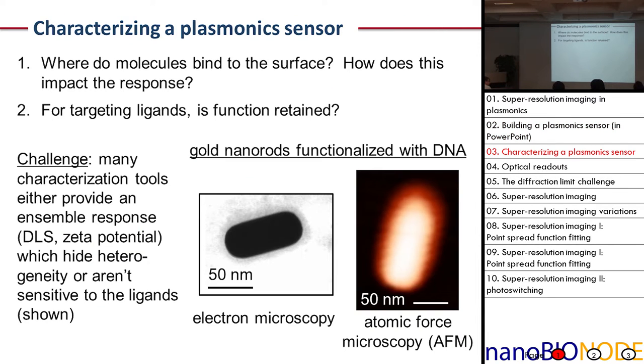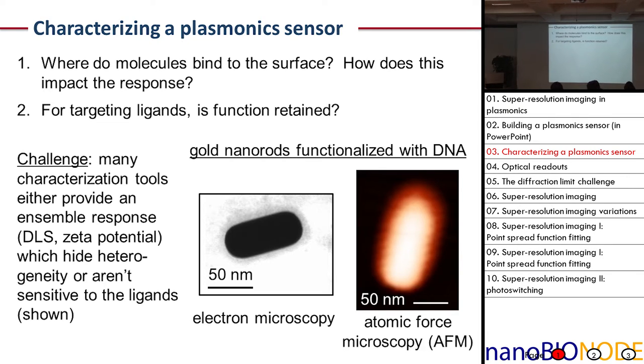But in reality, when we think about using plasmonics for sensing applications, which is often in biology, we have to ask questions like where are the molecules actually binding to the surface, and more importantly, how does this impact the response? We know from work shown this morning that you'll have regions on the surface of nanostructures with much more strongly enhanced fields, impacting the magnitude of the signal. Moreover, if you attach a ligand to target an analyte, you want to know whether that function is retained - you can attach as many antibodies as you want, but if they're all pointing the wrong way, you've made a garbage sensor.